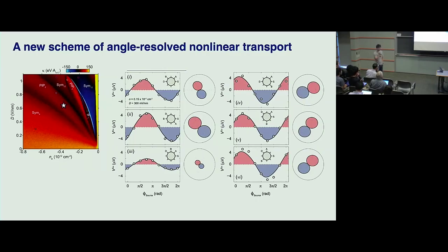I'm just showing a subset of the points. It's not practical to show all of them, but as you can see, even with some really weird configurations, the points fall right on the curve, and the curve is the fit using one single conductivity tensor, right? If you can fit all of the points with one single tensor, that means one, the fit is pretty good. We have a good handle on the tensor. Two, the sample must be very uniform, right?